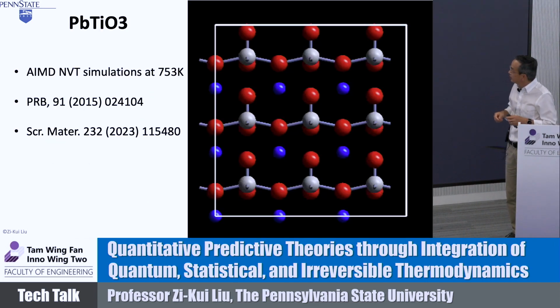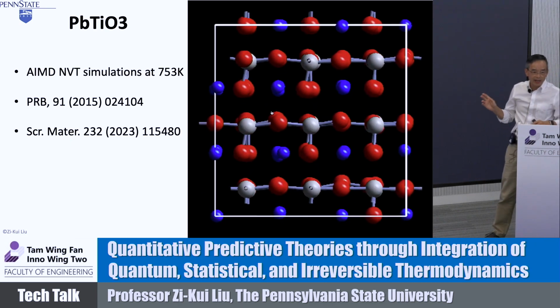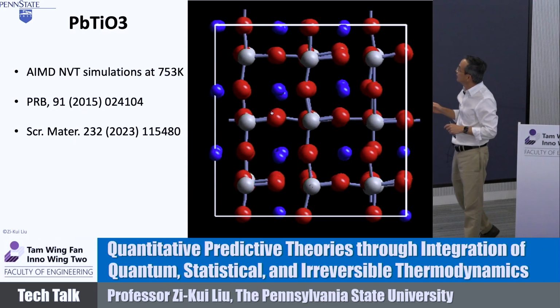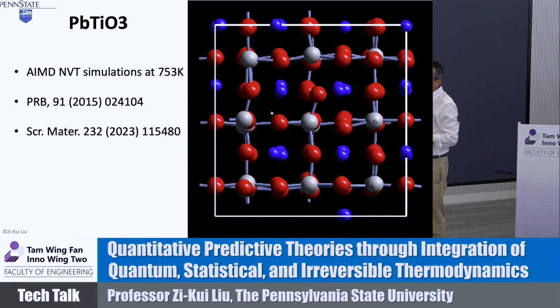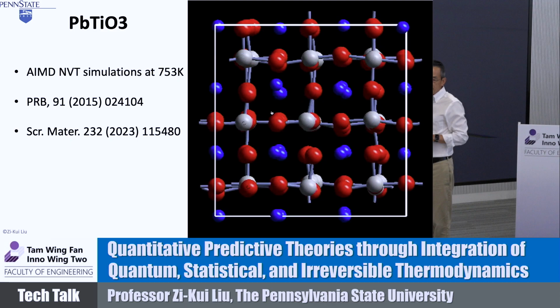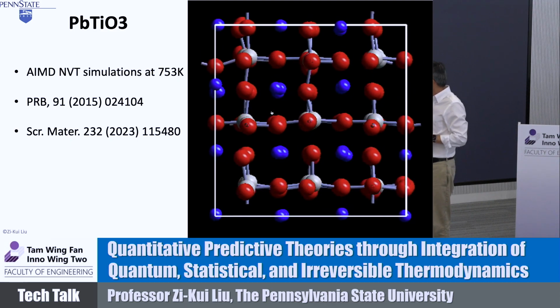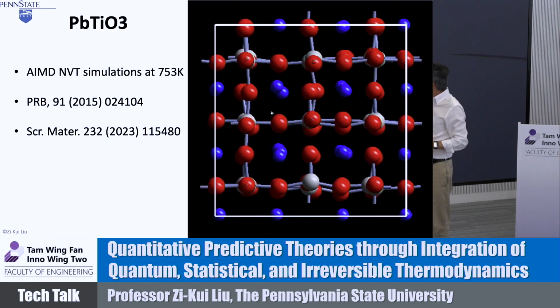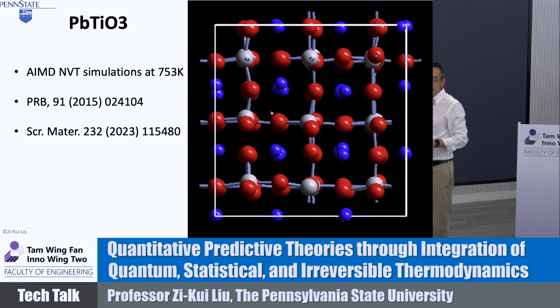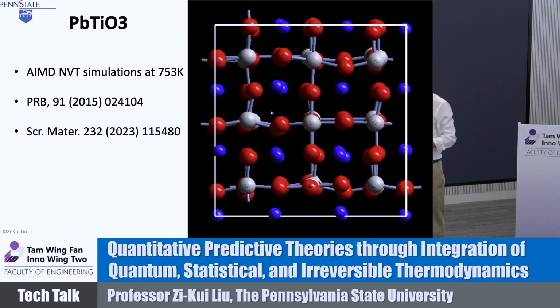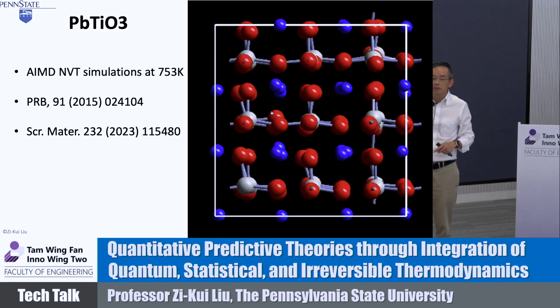Okay, so we did that. So they asked my student, a postdoc, to do the experiment, right? We do the AIMD simulation. Above that transition, you have a cubic, so you fix the cubic lattice. Then you do the vibration. Then you follow the atoms in the middle. You see that, right? The blue atoms are the titanium. So titanium never stays in the middle. The polarization goes in another direction, it goes in all directions. But it does go through the middle. So it stays at time zero in the middle, but it goes through the middle.